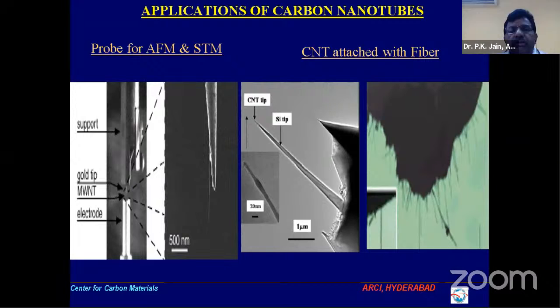It can be used as a probe material, like in our SPM or AFM or anywhere. The probe material always undergoes many chemical changes, so it has to be strong enough. That's the reason our FESEM, the field emission SEM, has come, because of the replacement of the cathode. Now the nanostructured cathode is there, and because of that the magnification goes very high.